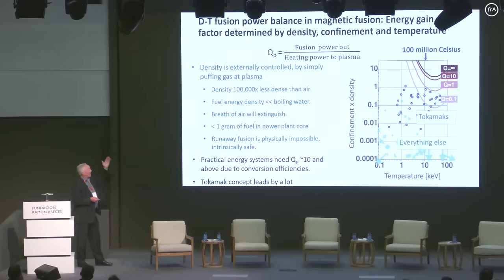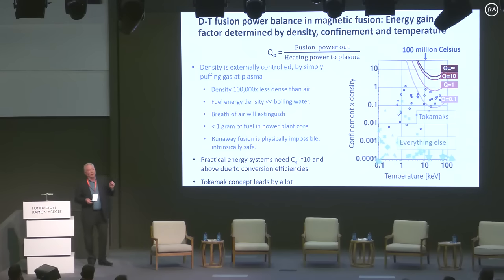What has not been achieved is the confinement and density product, because in this we have a few curves, and this shows the energy gain in the system. We apply heat to it, like lighting the match on your fire, but what we need is that the amount of fusion power greatly exceeds the heat that you're putting into it, and we call this capital Q.